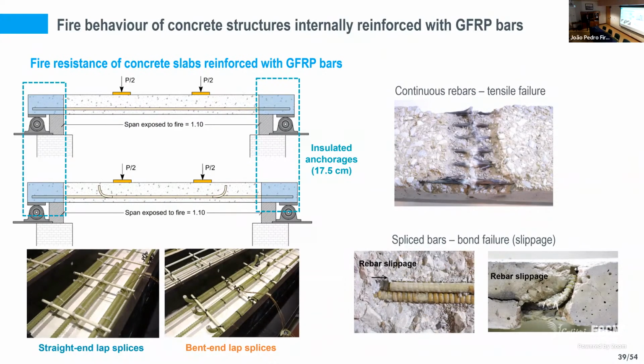With continuous reinforcement, the slabs failed due to tensile failure of the rebars in tension, whereas with the spliced bars, failure occurred as expected due to rebar slippage inside the concrete.